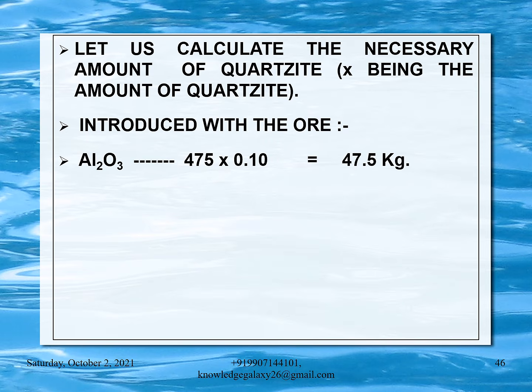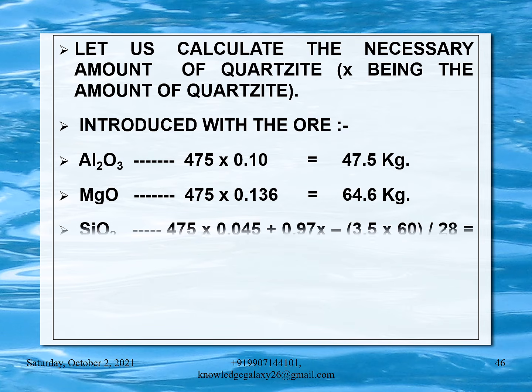Al2O3 which is introduced with the ore is 475 into 0.10 is equal to 47.5 kg. MgO is 475 into 0.136 is equal to 64.6 kg. SiO2 is 475 into 0.045 plus 0.97x minus 3.5 into 60 divided by 28 is equal to 13.9 plus 0.97x.